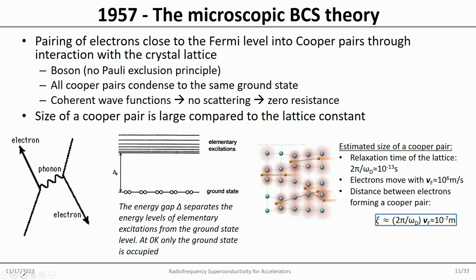theory then incorporated. So the idea is that you have a pairing of electrons into pairs. Basically you create an attractive interaction between electrons. Obviously electrons normally repel each other, same charge, but through interaction with the lattice, here depicted as a Feynman diagram with a phonon interacting with them, they create an attraction. So if you have two electrons, you have a boson, with a single integer spin. All Cooper pairs now condense into the same ground state. A Cooper pair is just two bound electrons, and they can form a coherent wave function. A coherent wave function will not scatter with the lattice. We got zero resistance. That's the explanation.